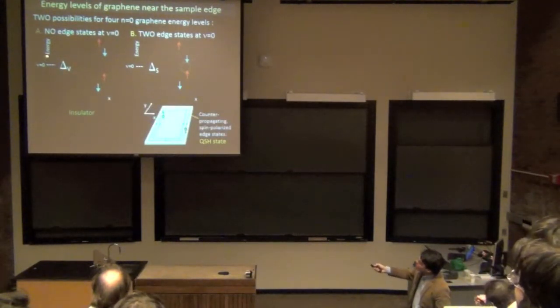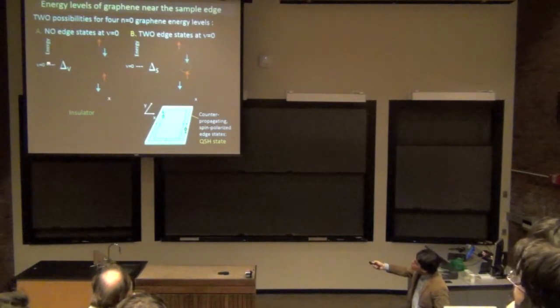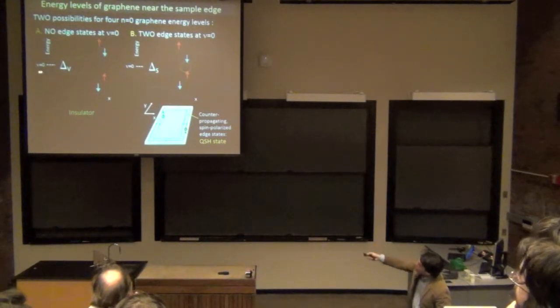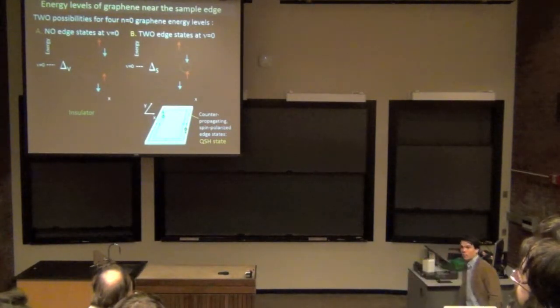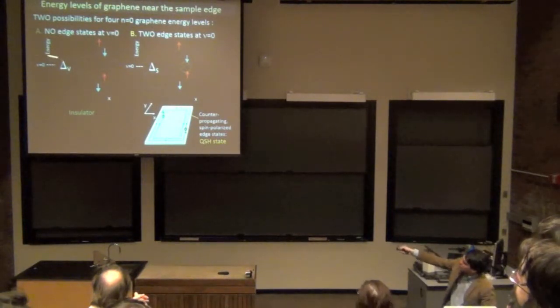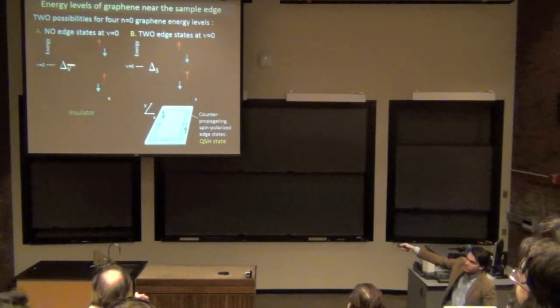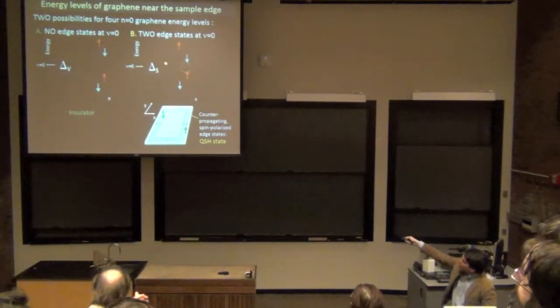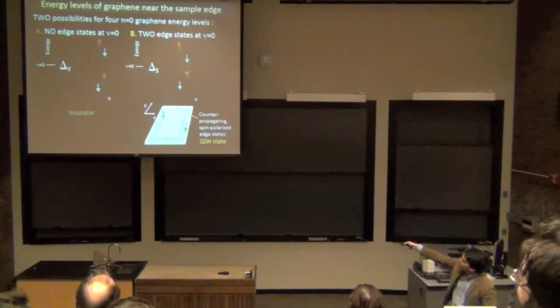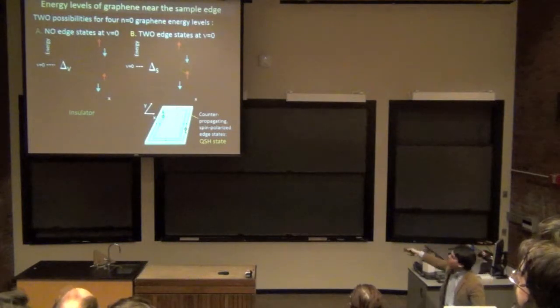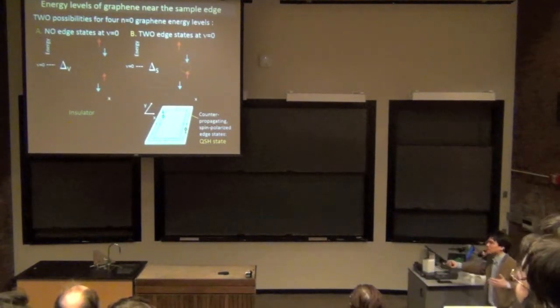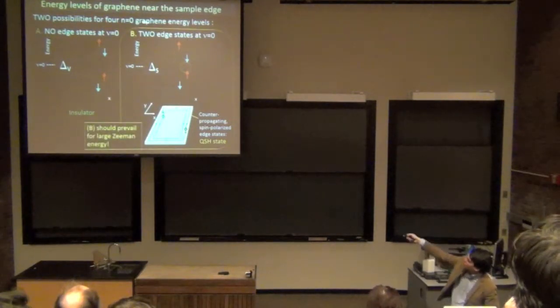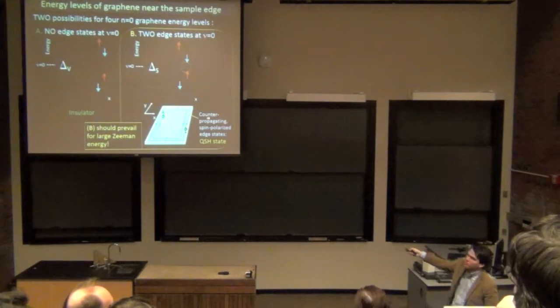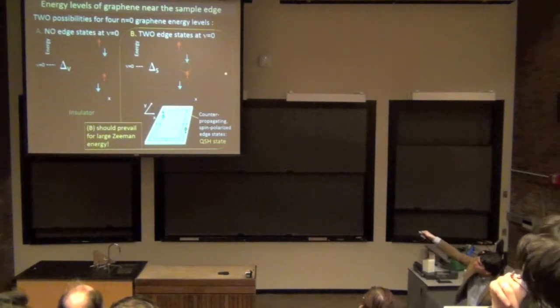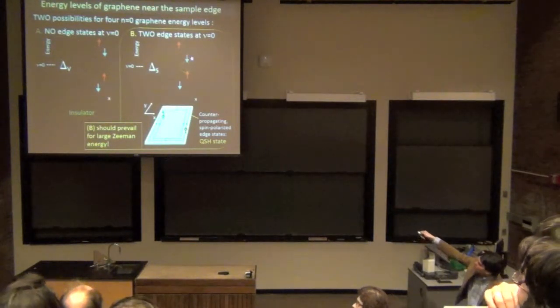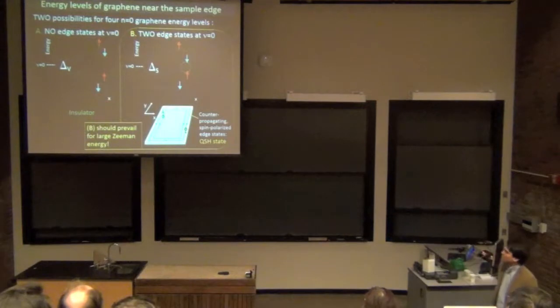The reason for that is that because these states are electron-hole symmetric, when you get to the edge of the sample, which is right here, two of them curve up and two of them curve down, and the order in which it occurs is really important. Because on the left-hand state, if you have a band here, there are no electronic states at the Fermi level. Here, if you place the Fermi level here, there are exactly two electronic states at the Fermi level. One goes one way, which is spin up. One goes the other way, which is spin down. So there's an experimental question: which one of these is it? One thing I wanted to point out is that state B should actually prevail for a sufficiently large Zeeman energy. If you have the Fermi level here, all the states below the Fermi level have spin down, and all the states above have spin up.